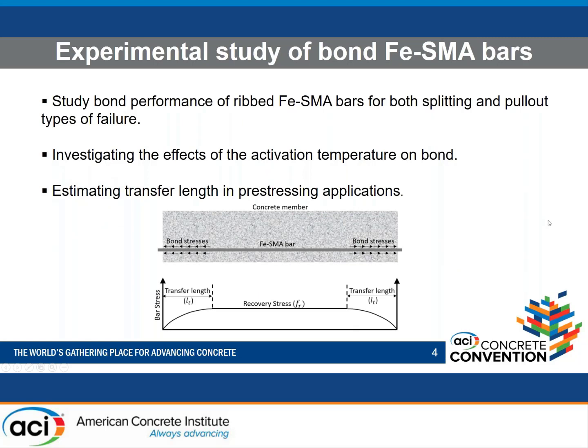So the objective of this study is to study the performance of ribbed shape memory alloy bars for both splitting and pull-out types of failure. Due to the possible effect of the activation temperature, we are investigating different temperature activations in order to see the influence of this temperature on the bond behavior and the bond strength. And finally, we will estimate the transfer lengths in prestressing concrete applications, because this material can be used for strengthening, can be used for concrete overlays, and it's important for practical applications to get an idea about the transfer lengths for that material.